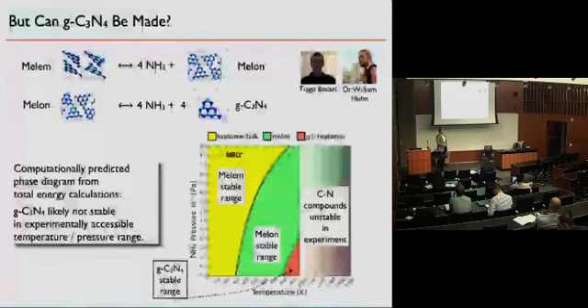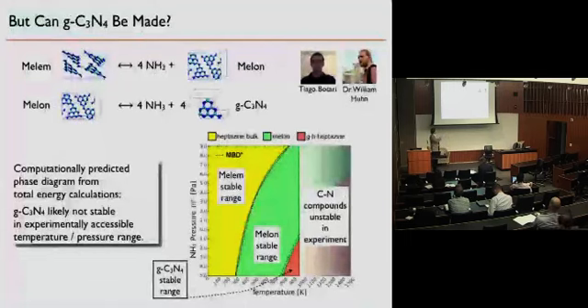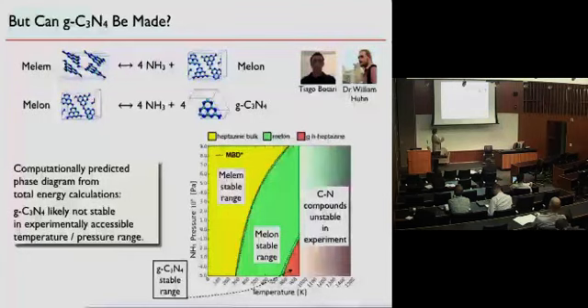of simple calculations based on the chemical reaction equilibria, and I'll just show you the outcome of that in terms of a so-called temperature-pressure phase diagram, where the relevant pressure is actually that of ammonia, which is one of the products that comes out of the material if you want to condense it further and further to become this final graphitic carbon nitride material here. It turns out that you can find ammonia temperature and pressure ranges that are experimentally relevant, both for this single molecule as well as for the melon, which is photocatalytically active. But the range where you can make the hypothetical graphitic carbon nitride material is very, very small.